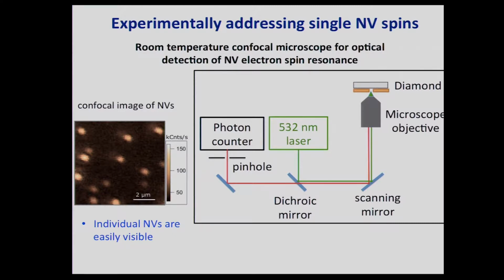So here on the left is a confocal image of NV centers where we scan the laser across a few micron size area of the diamond. And these bright spots each correspond to a single NV center. We can confirm this through techniques that were referred to earlier, anti-bunching techniques from quantum optics, where we can really confirm the presence of single NV centers. The point is that these are bright and individual ones are easy to locate.